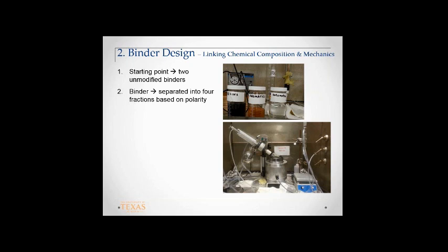And how do you separate them? There's an ASTM procedure with lots of detail, but if you recall your high school chemistry, there was this thing called like dissolves like. You mix a polar material with a polar material, it'll dissolve. You mix a non-polar with non-polar, it'll dissolve. You mix a non-polar with polar, it will not dissolve. So the way you separate all of this is you take solvents of different polarities